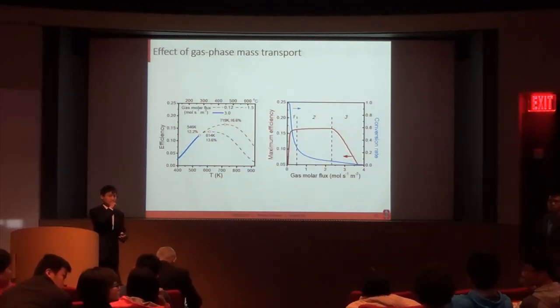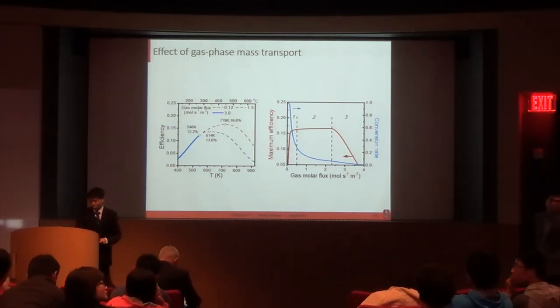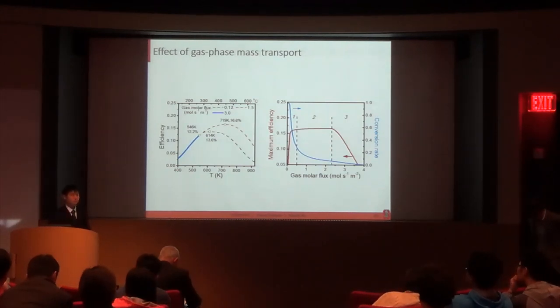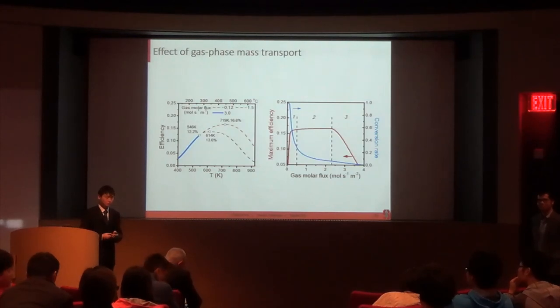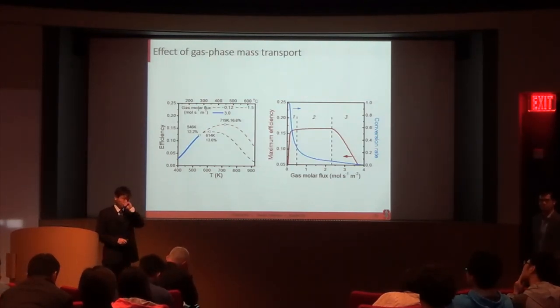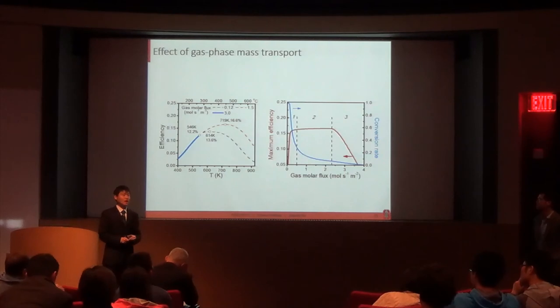So you mentioned degradation of some of the cobalt phosphide catalyst. So when you move to elevated temperatures with the bismuth vanadate and the cobalt doped bismuth vanadate, how stable are these materials? Have you seen any degradation over time scales? At elevated temperatures, like 400 degrees Celsius, when you're looking at photovoltage, do you know that these materials are stable in these temperature regimes? Because some materials do degrade.